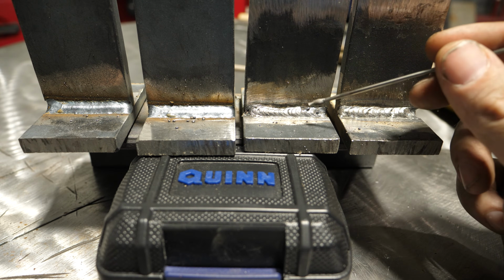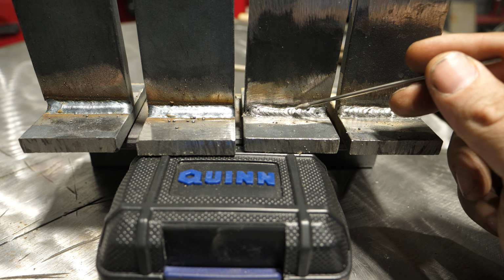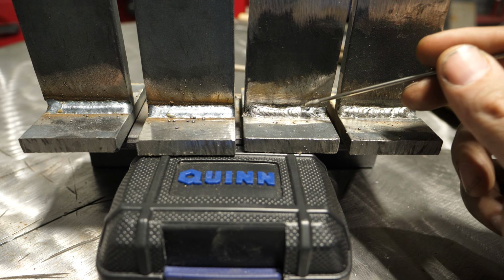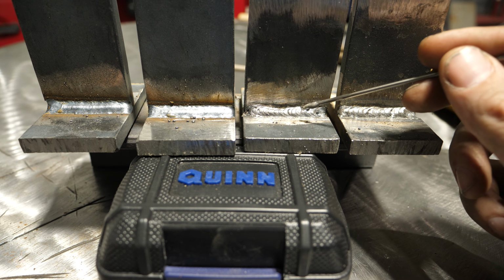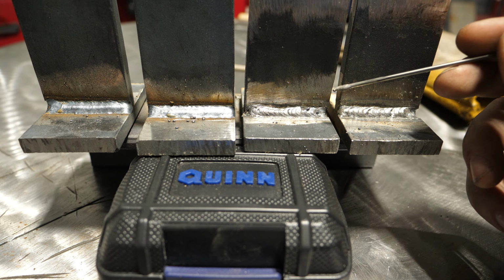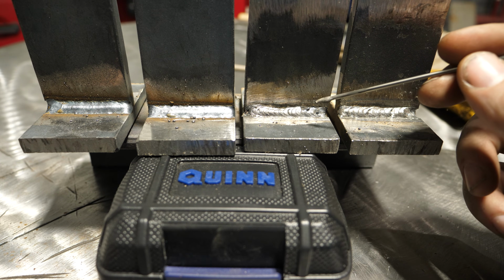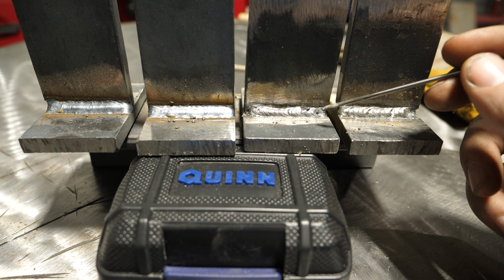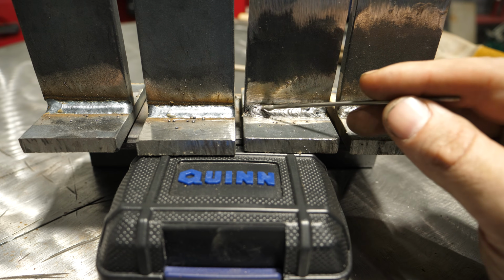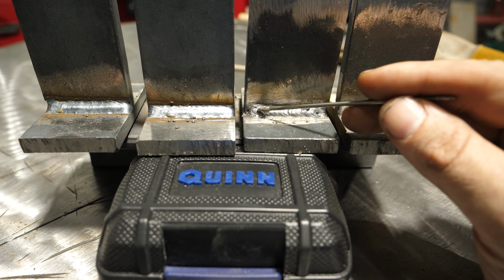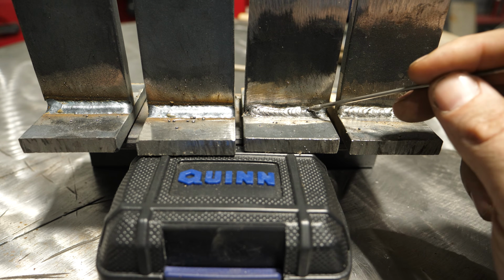Now, the interesting thing is that flux core wire self-shielded can technically weld 3/8 plate with a 200 amp MIG welder. However, there's a lot of undesirable side effects. It may be a little bit hard for you to see, but there's evidence of porosity here on the toe line.